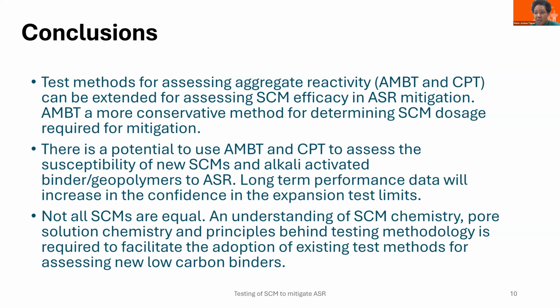Last is that not all SCMs are equal. Therefore, I think an understanding of the SCM chemistry, the pore solution chemistry, and how the SCM impacts that is needed, because ASR in particular is very dependent on the pore solution chemistry. And the reason SCM mitigates well is because it drops the alkali in the pore solution over time. It's also very critical to understand, as I've mentioned, the principles behind each testing methodology, because if you don't understand the test, you cannot just extend it.